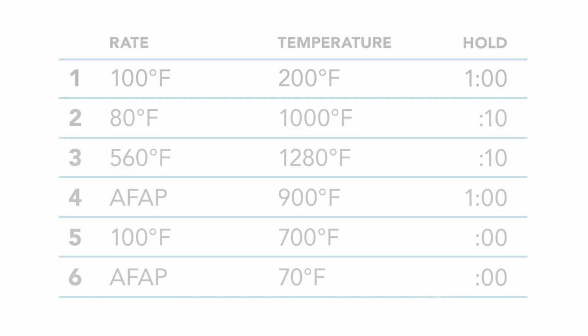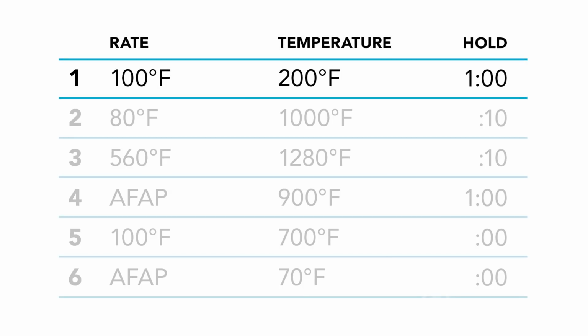And what I'm going to do is I'm going to hold the kiln at about 200 degrees Fahrenheit for an hour before continuing the initial rate of heating. Without the drying cycle, the piece could thermal shock during heating. This is because any area that still has water on it will be held below 212 degrees as the kiln starts to heat, and any area that doesn't have water on it will heat at roughly the same rate as the kiln. This means that there would be a temperature difference that could become significant enough to cause strain that could make the piece break.